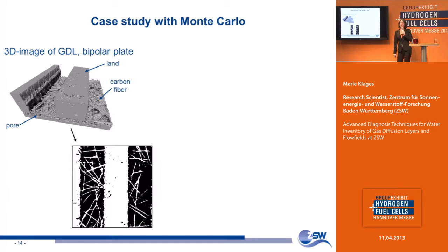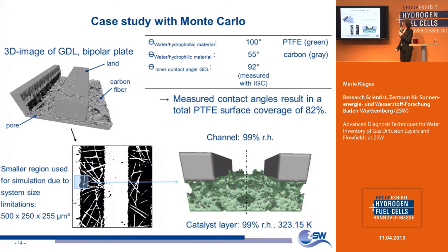Well, for Monte Carlo simulation, we took those three-dimensional fuel cells, divided that in binary images of the different layers, with each a thickness of the resolution of 5 micrometers. We took a specific region, imported that in Monte Carlo, and simulated a hydrophobic region inside the fuel cell, inside this GDL, with specific conditions similar to the synchrotron tomography.